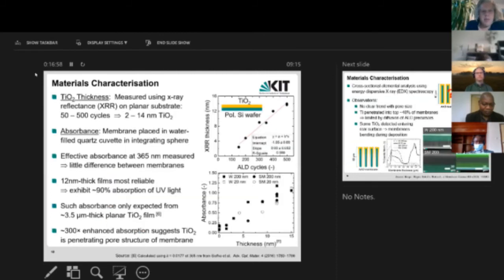So, starting with some materials characterization of the thin films. We commonly used X-ray reflectance as a measure of the thin film thickness. But I should emphasize that the thickness we're measuring, shown on the top right, is the titanium dioxide film as deposited onto a polished silicon wafer. So it's not on the membrane, it's on a flat, polished surface. There the graph shows a very linear relationship between the number of cycles and the film thickness. So with our process we can get anywhere from about 2 nanometers as the thinnest, up to about 14 nanometers as the thickest films.